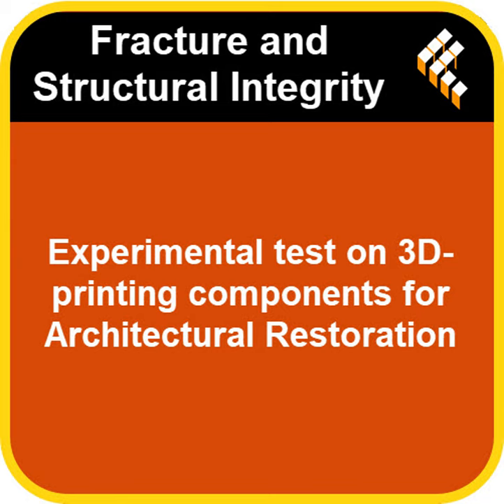Okay. In the pure tension test, that pulling force is spread pretty evenly across the entire cross-section. Every bit of plastic is feeling roughly the same stress. Right. Uniform pull. But in bending, it's different. Imagine the beam bending downwards. The top surface gets squashed, compressed. The bottom surface gets stretched, tension. And the stress is zero right in the middle, and it increases as you move toward the top or bottom edge. The maximum tension only happens right at the very bottom fibers.